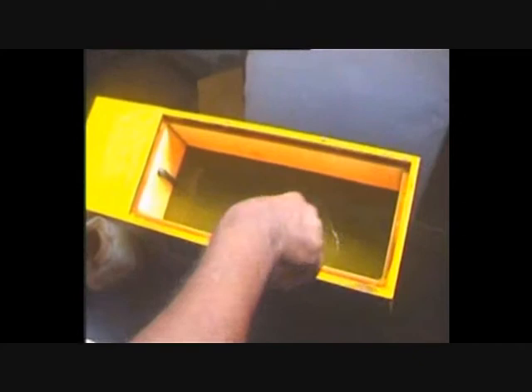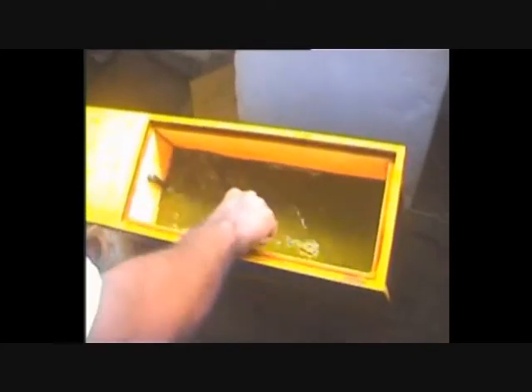Step 5 - Etching: In this process we use a tank filled with ferric chloride solution. We keep the copper clad sheet in this solution for about 15 minutes. The copper will be removed from the non-conducting path on reaction with ferric chloride. Then the etched copper clad sheet is cleaned with thinner.